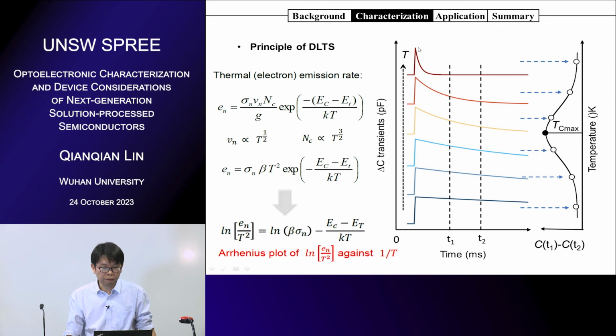And if you look at different transient capacitance at different temperatures, this is a typical DLTS measurement, so you will get different cases. At low temperature, the emission rate is low, so the capacitance changes very slowly. At high temperature, the capacitance changes very quickly. If you have an observation window with T1 and T2, you can see the difference within this window, and you will get a curve like this. At low temperature, the DLTS signal is low, and at high temperature it is also low. At a certain temperature, the DLTS signal will be very high.